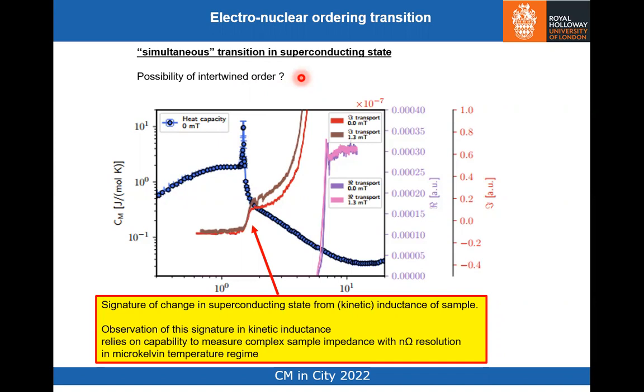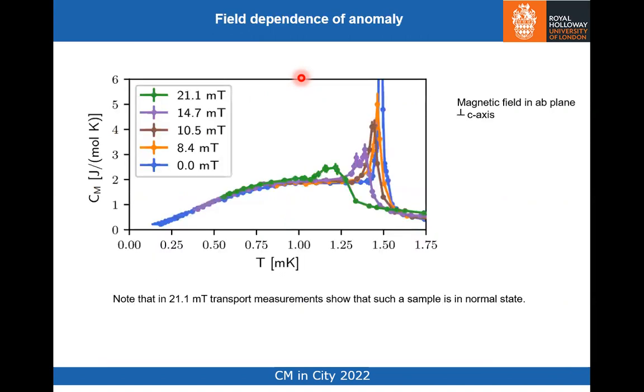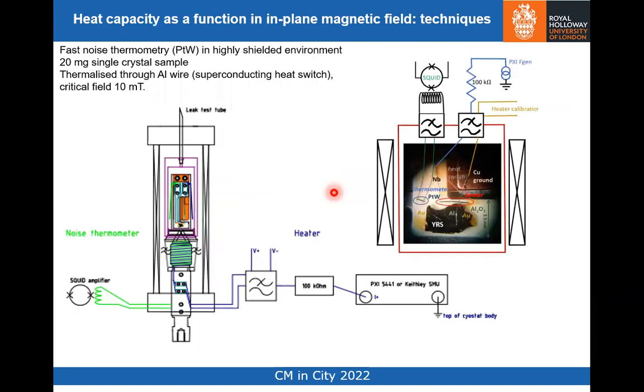So I now want to spend a little bit of time on the details of the heat capacity measurement. We apply in-plane magnetic fields, and what happens is this sharp anomaly that we saw here at about 1.5 millikelvin shifts down in temperature and broadens. I want to emphasize that at 0 magnetic field, we had this sharp anomaly that coincided with the superconducting transition, but at 21.1 millitesla, we see this broadened anomaly in the heat capacity, and at that field, the sample isn't superconducting. It's important to bear that piece of experimental information in mind.